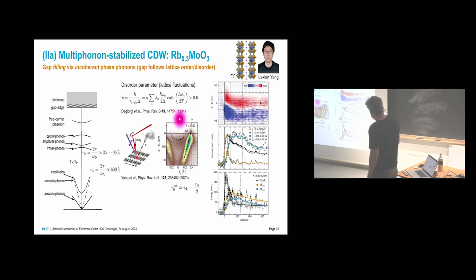Here, the charge density wave gap is not so clearly visible because the energy resolution is not high. Then you go to the difference ARPES map, and what you see is red is added intensity and blue is removed intensity, and in between you have the gap. And then you see how red enters into the gap region on a time scale which is relatively fast. This line here is half of the oscillation period of the relevant phonon, and this intensity filling into the gap is much faster than this coherent process.